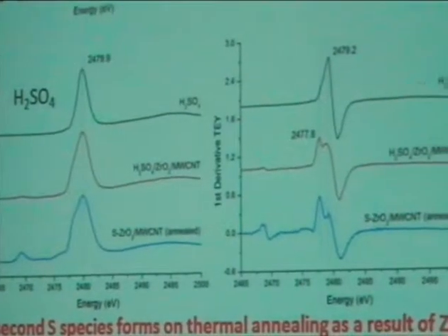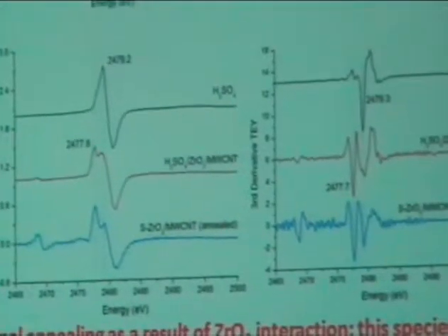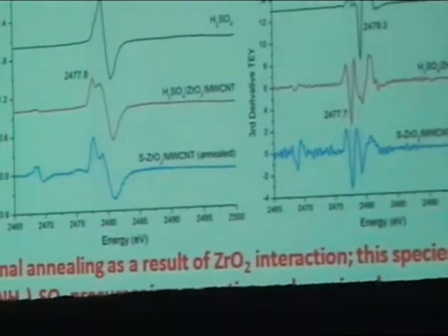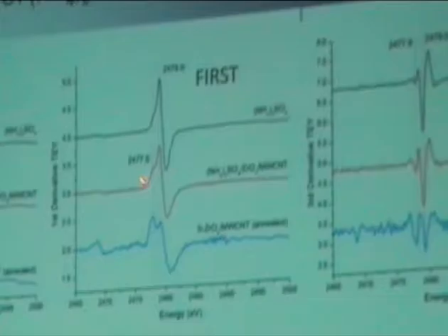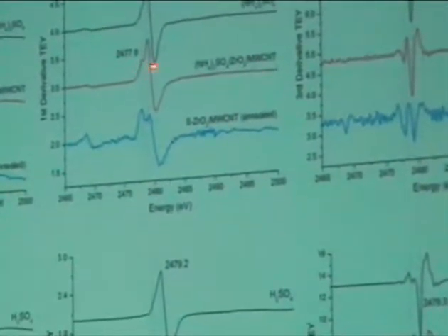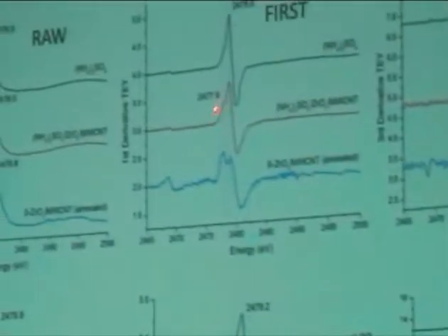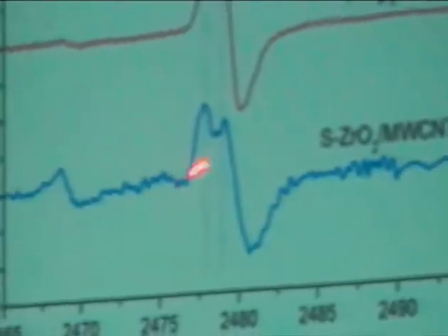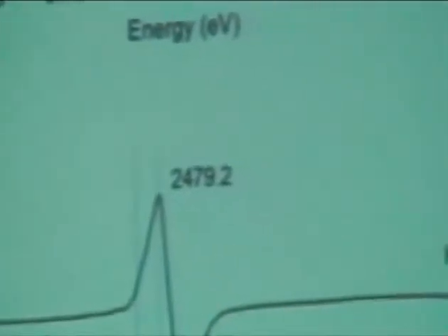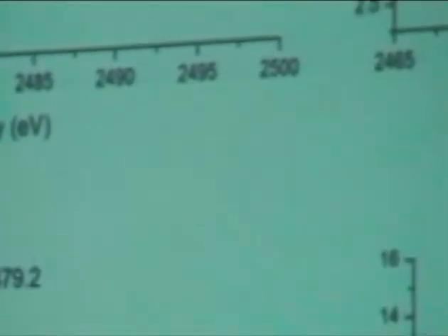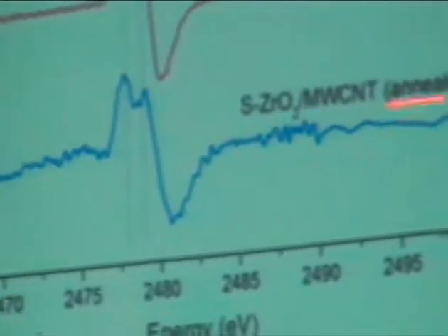If you take the first or the second derivative, you will see that you now can see the beginnings of a second peak here, just after it's been impregnated. But when you anneal at 450, the second peak becomes distinct, both in the first derivative or the second derivative. These are normalized, so that's just the pattern, not the intensity you look at.